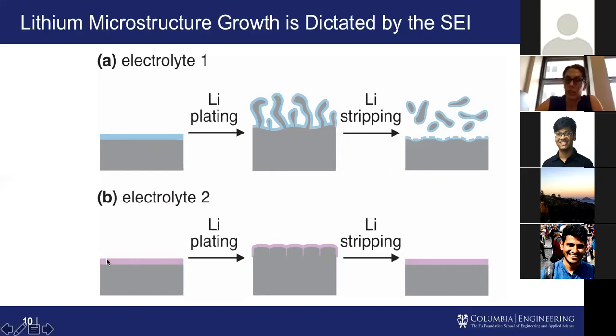If you have a good SEI, what would happen is you get these lower surface area structures that are more flat on the surface. So they're not going to jet off and pierce the separator at any point during battery operation. Whenever you start plating lithium on the surface, it's very smooth. And when you take it away during discharge, it's also very smooth. So if you have a good electrolyte, it's a very reversible process. If you have a bad electrolyte, this process becomes very irreversible.